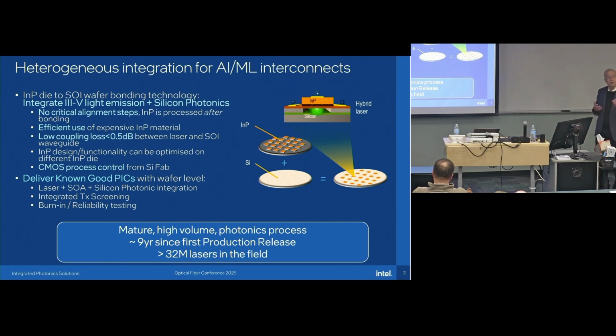If you try to do hybrid bonding, soldering a laser close to a PIC, it's hard to get less than a dB loss in there, and you get reflections. This is much better - we get down literally below a 10th of a dB. The other nice thing is you can use known good die when you combine it together.